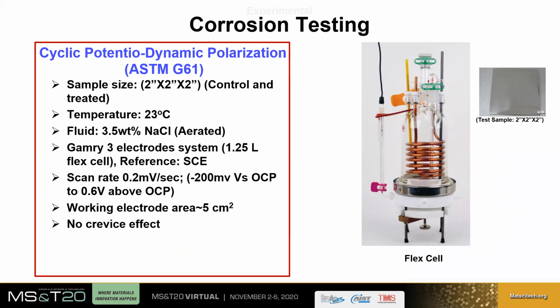Further, to evaluate corrosion properties after nitriding, they were subjected to cyclic potentiodynamic polarization test as per ASTM G61. Testing is done at room temperature, 23 degrees centigrade, in 3.5% NaCl solution. We have used a Gamry three-electrode flex cell. The importance of this flex cell is that the working electrode area is 5 square centimeters, and we do not see any crevice corrosion effect. So in all the testing, we do not have any crevice corrosion, and we have clear data on all our test samples.